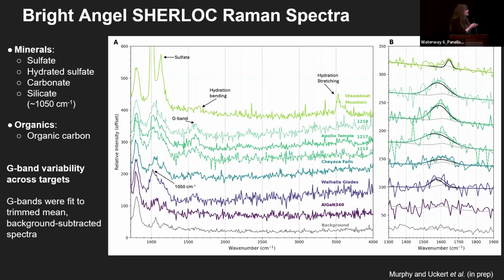So if we zoom into the G-band area and look at panel B, it's kind of hard to see here, but there's a slight hump in that region in our background signal. So we fit that here in the gray line, and then we deconvolved it from all of our peaks to make sure we were just looking at the G-band, which is shown after we deconvolve that, in the black here. Again, we don't see anything in our Algan target. And if we look across these G-band signals or organic carbon signals, we see that they vary in their peak position and in their bandwidth, which is the full width at half max here. And if we look at our hydration bending mode that's in this bassanite, we see that it's much more narrow than those G-bands, and it's at a higher wave number.